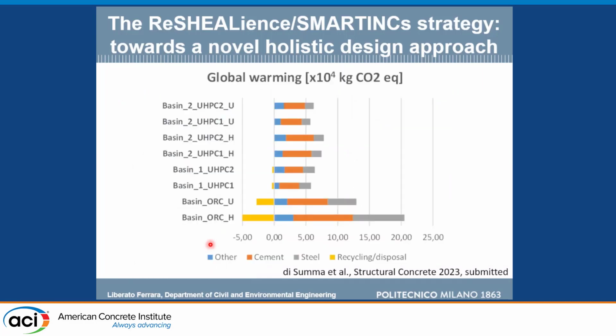Then you plug into your life cycle analysis software all the data that you need, and you end up showing that in the end, UHPC, with different mix compositions and different mechanisms of aggression, is always more sustainable. This is just one indicator than the ordinary reinforced concrete solution. It's also interesting to see this. These yellow bars for ordinary reinforced concrete show negative. Actually, when you have to dispose of steel, most of the life cycle analysis tools consider steel as completely recyclable, and so account for the negative value. They do not consider concrete as recyclable, but we know that it is. So this is also something that we have to work on, in order to have life cycle analysis tools that really consider all the potential benefits of this kind of materials.